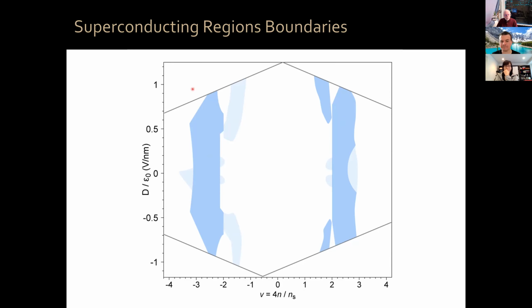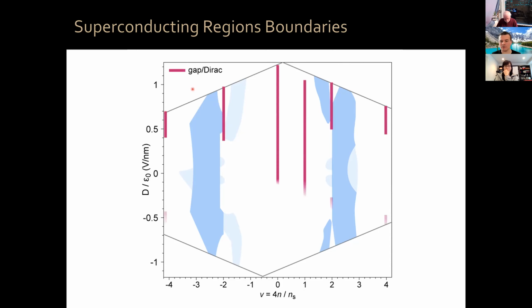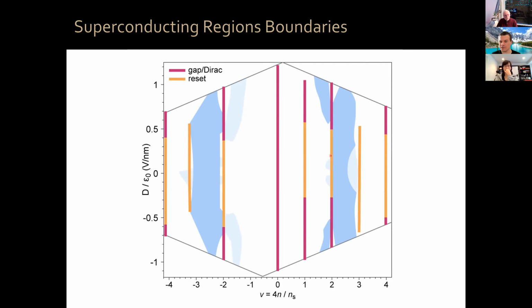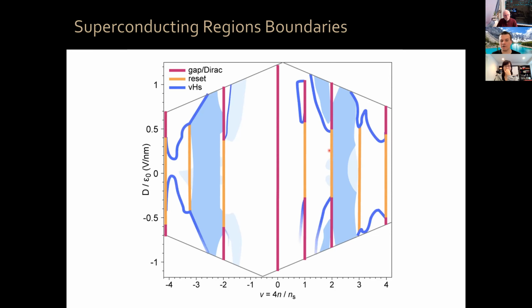Okay, and then I'm going to now superimpose in this diagram the regions in the normalized Hall density where we saw gap Dirac behaviors here in red, reset type of behaviors in orange, and Van Hove singularities in these dark blue lines. And now something is emerging. Okay, you can see that at low displacement field, the superconductivity is mostly bounded between the resets that occur at 2 and 3 and -2 and -3. But at high displacement field, your superconductivity is bounded by Van Hove singularities and gap Dirac points.